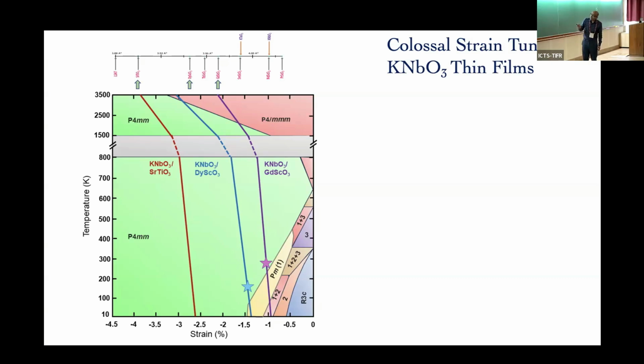So zero strain, it's got a bunch of transitions. It's not zero stress, but zero strain. But you just need about 1.5% compressive strain. And all of this green region is just one phase, tetragonal phase. Okay, you squeeze it like this, it pops out. It's tetragonal, it's long this way and compressed this way.